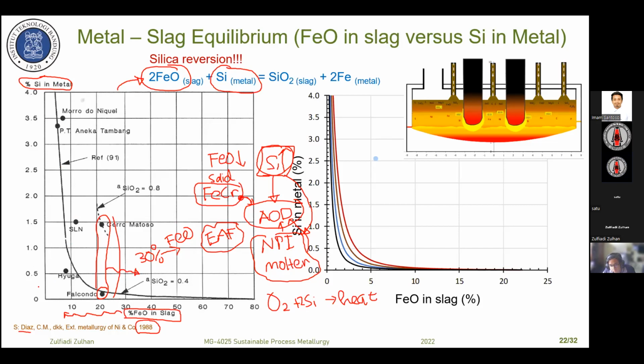The common silicon content in current operation is kept between 1 to 2%. If we have high silicon content, for sure, in the AOD converter, we should add more flux again. So more energy, more slag will be produced. More slag could also mean more nickel losses into the slag. The optimum is between 1 to 2%, not 4%, for example. 4% is too high, and the energy release is also very high if we have 4% silicon in the ferronickel.